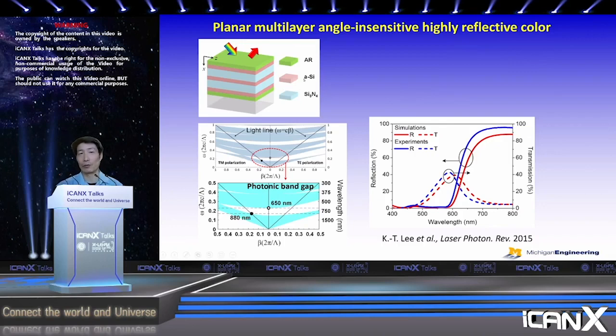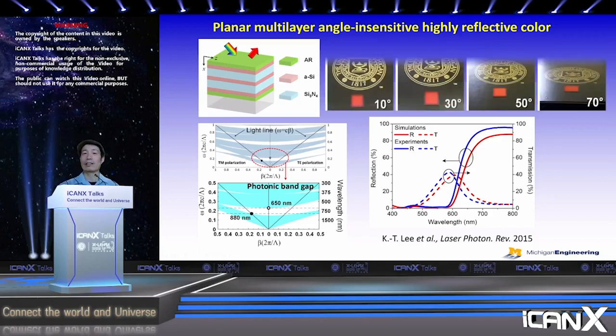Amorphous silicon is absorbing. Silicon nitride is transparent. Arranged in such a fashion, it's like a photonic crystal, but only involves a few layers. To get the angle independence: optical resonances generally depend on the angle, right? So to put it simply, you want to make the band flat so that it has less angle dependence. You can see this red sample, and indeed, even at 70 degrees, it still remains red.